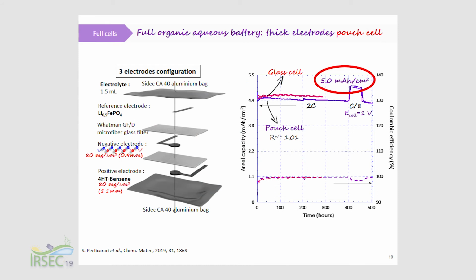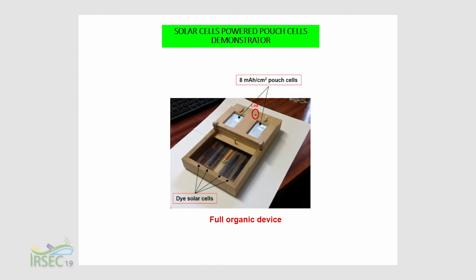So we have done some coin cells, glass cell experiments for full cells, coin cells, and also pouch cells. And here I show you that with pouch cell we can cycle several hundred of cycles. We get 1 volt output voltage, and for thick electrodes of 5 milliampere hour per centimeter square. So here it's only a summary of a lot of results, of course. So these correspond to our target. And thanks to these results, we have fabricated in the lab some pouch cells with 8 mAh per centimeter square, and we have fabricated such a demonstrator where we charge our pouch cells with dye solar cells made at the organic chemistry lab next door. So all this system is a full organic device.